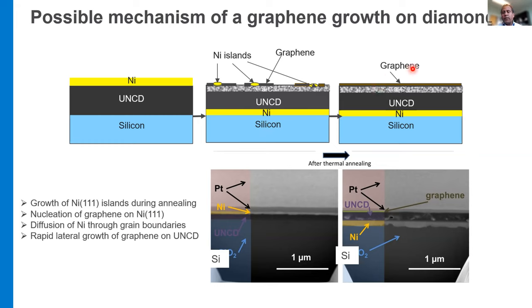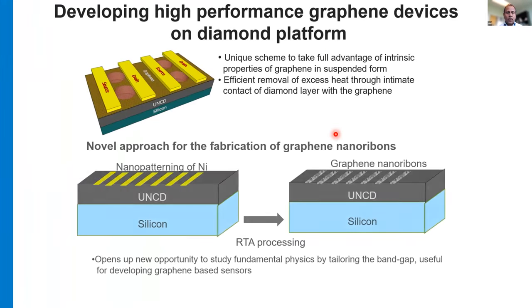So whenever you make devices on top of this, they are electrically isolated from the nickel, because you have insulating UNCD here. So this naturally forms a very good way of converting the diamond, with the nickel, into graphene, and gives the ability to form very good device structures on top of it. With this process, we can take full advantage of the intrinsic properties of graphene, like overhanging or suspended graphene, because whenever graphene is in suspended form, that's where you get very nice properties of the graphene.